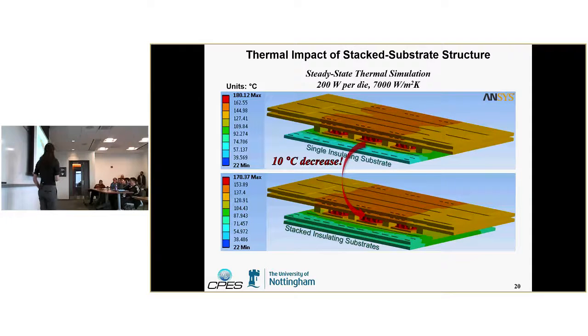And the reason for this is the added heat spreading that you get from that second insulating substrate. We're using aluminum nitride, which has very high thermal conductivity. If you use different ceramic materials, you don't get as much of a benefit. It's also, of course, going to depend on the heat transfer coefficient of your cooling system. But in general, it doesn't necessarily hinder the thermal performance, which is a good sign.